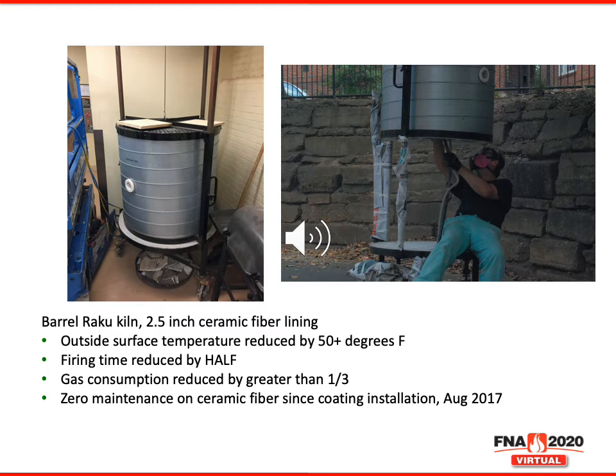The clay studio at NC State University also utilizes a barrel raku kiln with 2.5 inches of ceramic fiber lining. This time, approximately 1/8 of an inch of ceramic coating was applied, and the outside surface temperature was reduced by 50 plus degrees. The firing time of the kiln was reduced by half. The gas consumption reduced by greater than 1/3. And since August of 2017, NC State has done zero maintenance to the ceramic fiber since the coating installation.